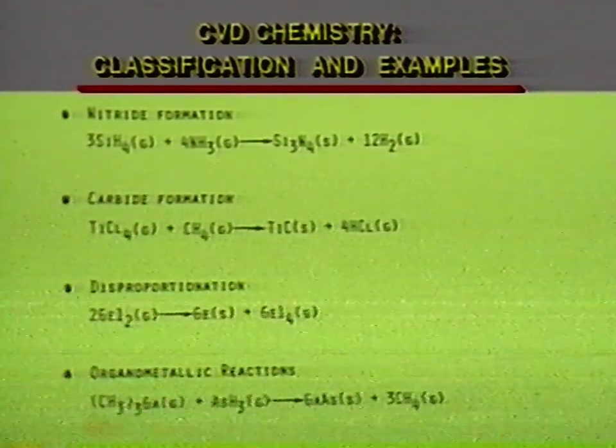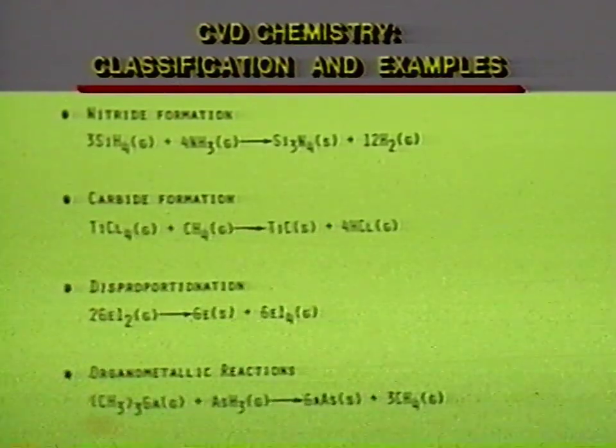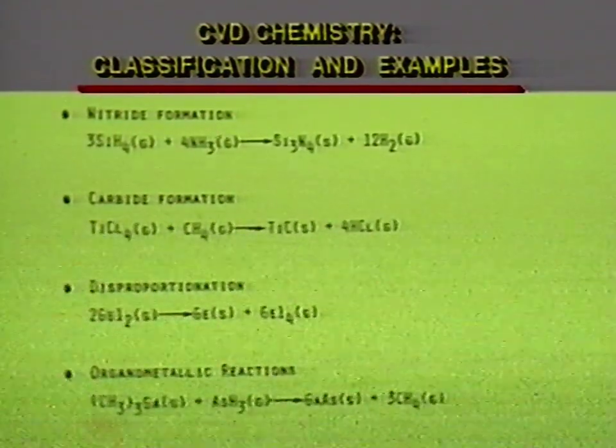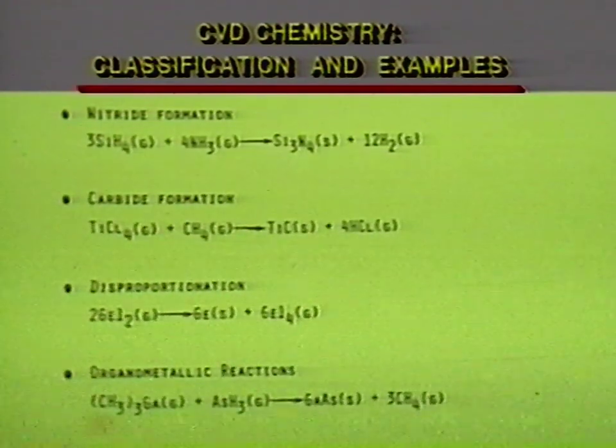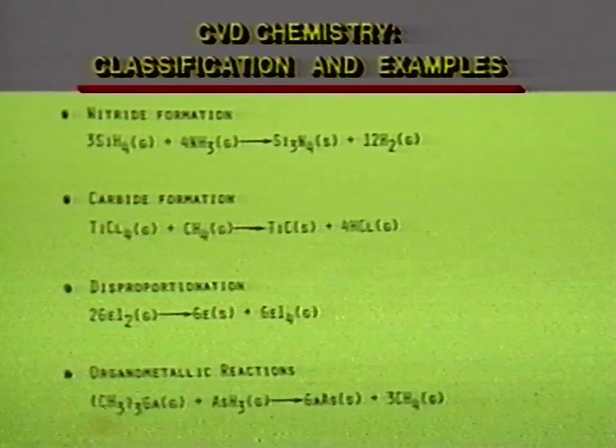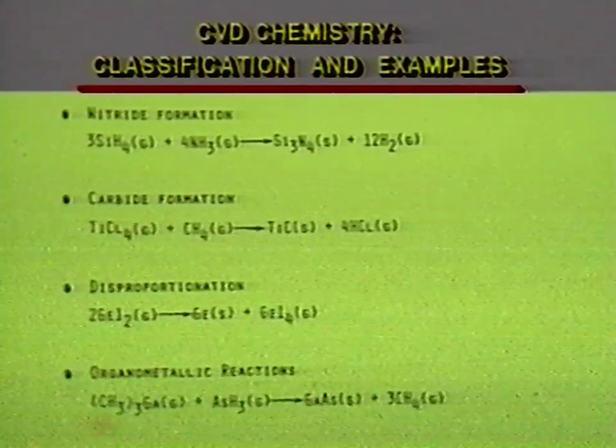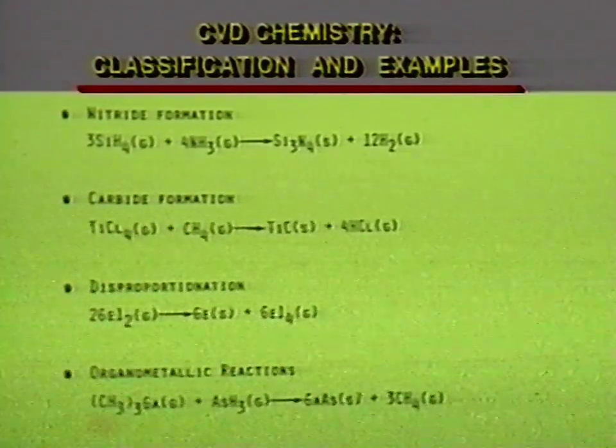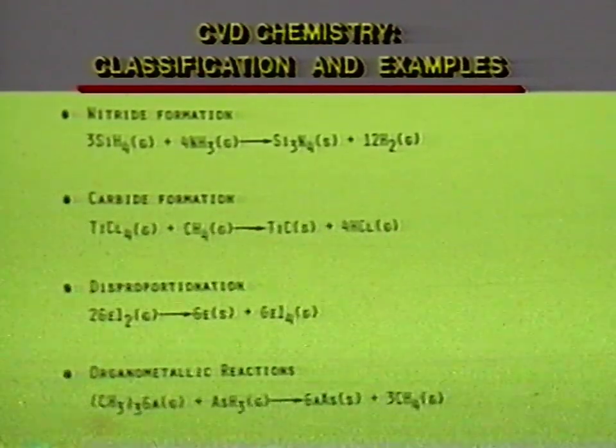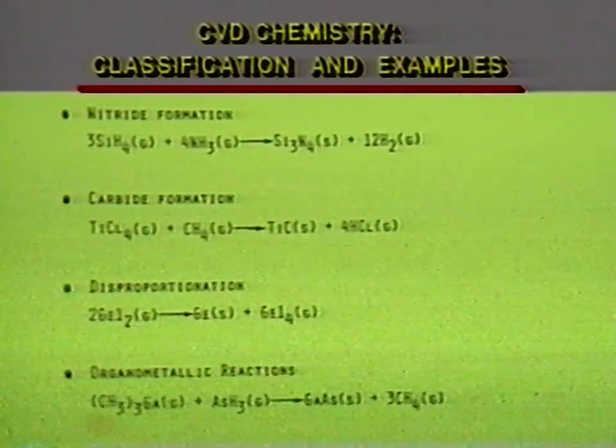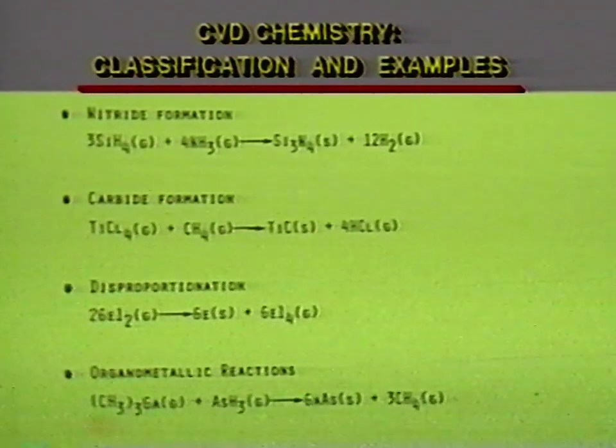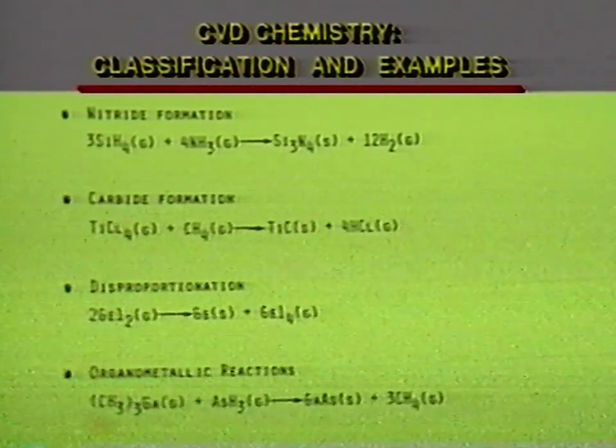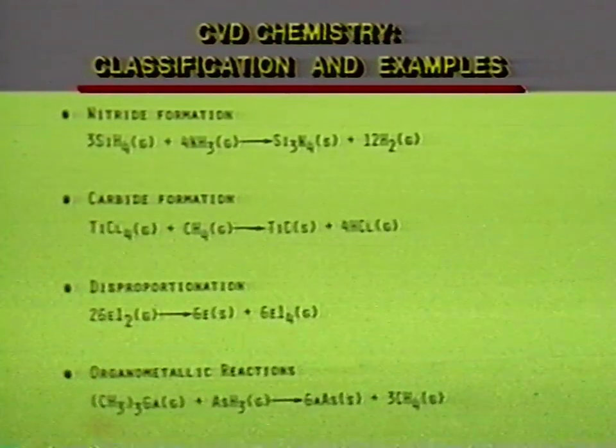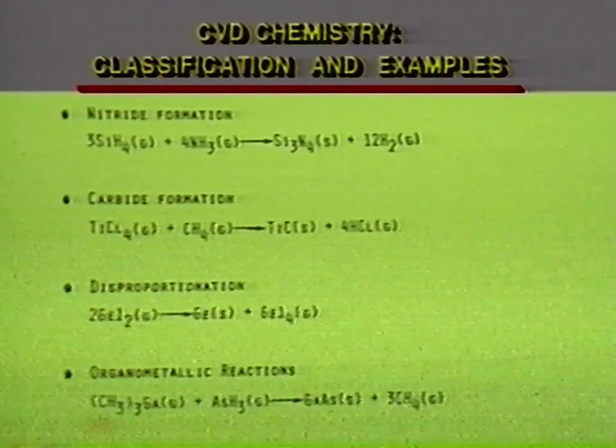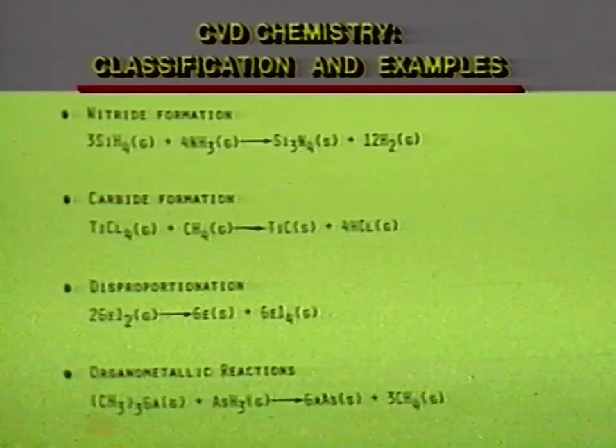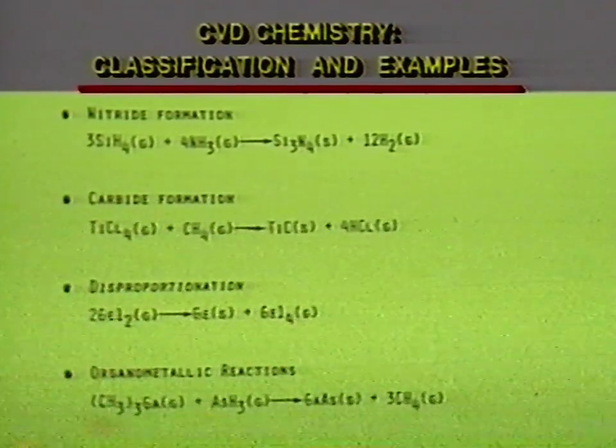Now, this one would be done, for example, at the temperature of 800 degrees centigrade if we use LPCVD, to give you a feel for that. Now, carbide formation is shown down here using titanium tetrachloride and methane to form titanium carbide layers and HCl. Disproportionation is another type of reaction. In this case, we have germanium diiodide forming germanium and germanium tetraiodide, depending on the temperature of the system. It can be a reversible reaction.